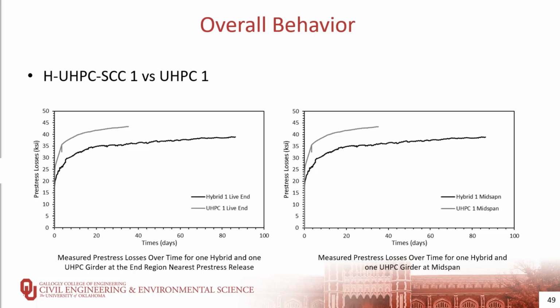These figures present the comparison between the hybrid 1 and the UHPC girders, where both girders were prestressed to 180 KSI, and they both had the same 5-foot reduced web section. Here we can see that both girders had a similar trend in terms of prestress losses over time at the live end region and midspan. The losses over time for both girders were similar at their live end region and midspan.